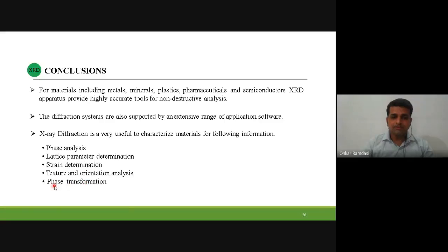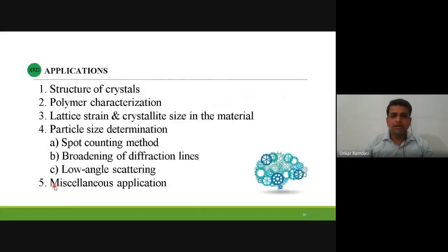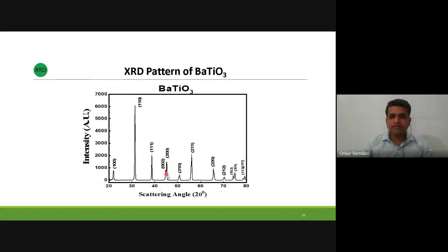So whenever you see, let's say this is BaTiO3 material, now it is splitting at this 45 degree. Now we know that BaTiO3 is a ferroelectric material, and it has a Curie temperature at 120 degrees Celsius. It means that after 120 degrees Celsius, it will become a paraelectric material. Curie temperature means ferro to paraelectric conversion. At paraelectric, the structure will be cubic.